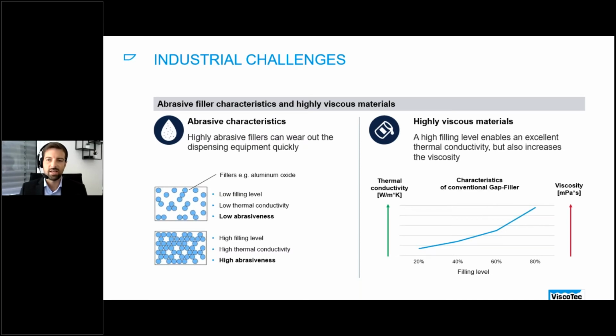So what are further process requirements or challenges? Abrasive filler characteristics and highly viscous materials. Thermal interface materials are highly filled to achieve a maximum thermal conductivity. That's the goal, definitely. But usually ceramic particles, for instance, made of aluminum oxide, are used. And a high filling level not only enables an excellent thermal conductivity, it also leads to a high abrasiveness, which can wear out the dispensing equipment quickly, as you can see in the illustrations below. And furthermore, as can be seen on the chart on the right side, as soon as the ceramic particles in the gap filler are increased, the overall viscosity is increased as well, which slows down the manufacturing process and finally contradicts a cost-efficient and fast production.